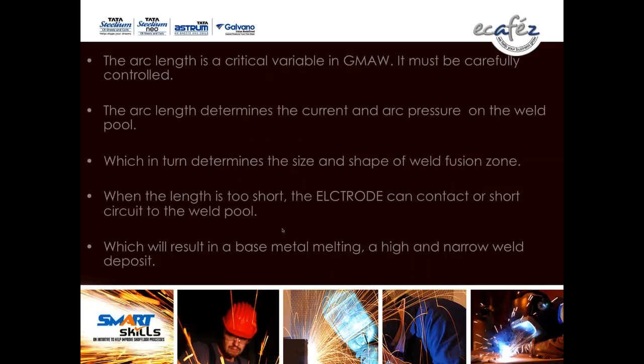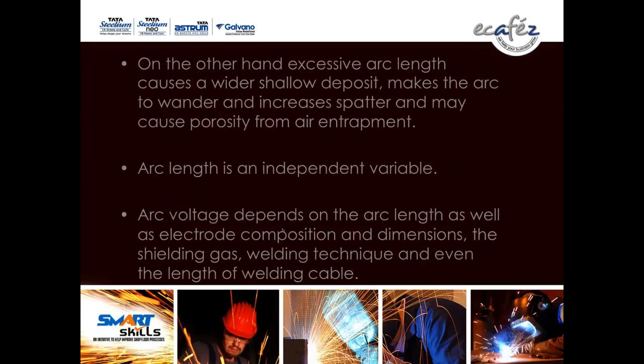Now the arc length. The arc length is a critical variable in GMAW. It must be carefully controlled. The arc length determines the current and arc pressure on the weld pool. When the length is too short, the electrode can contact or short circuit to the weld pool, which will result in base metal melting and a high and narrow weld deposit. On the other hand, excessive arc length causes a wider, shallow deposit, makes the arc wander, increases spatter, and may cause porosity from air entrapment. Arc length is an independent variable in the MIG process.